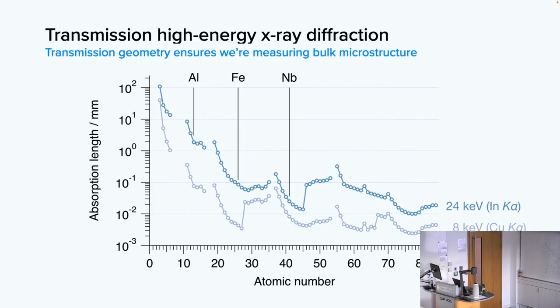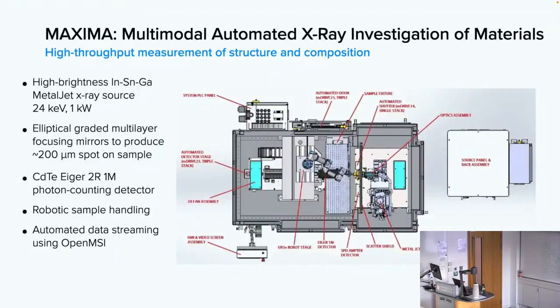Doesn't mean we can't look at thinner things, or thicker things. It just means that it takes a little bit longer. Where we do run into trouble is if we're now starting to look at things like the second row transition metals, right? So things like niobium, these absorption lengths now are pretty short, on the order of a few tens of microns. So we have done niobium. We can look through 100 microns or so. It just takes longer, right? We have to count longer. So we don't get our 10-second count times on that material.